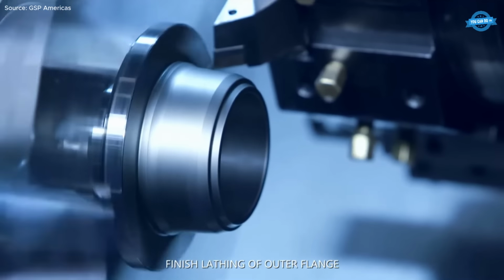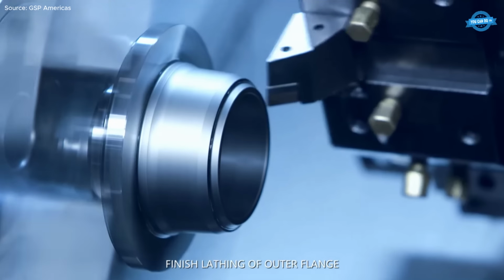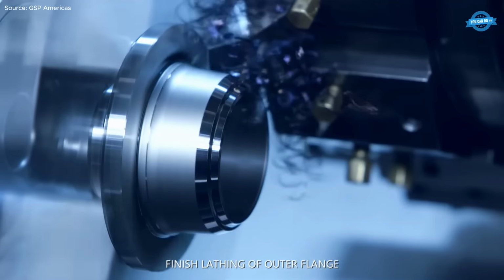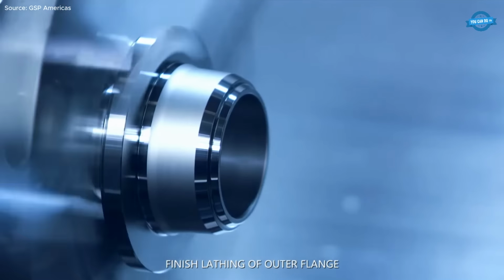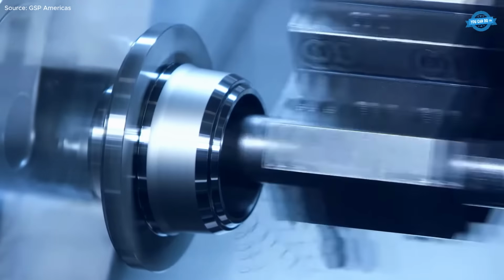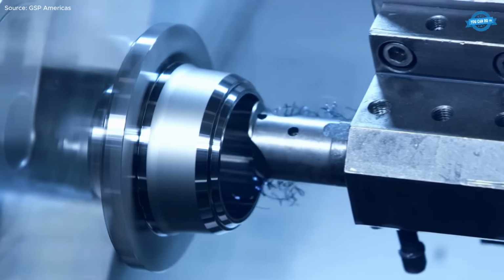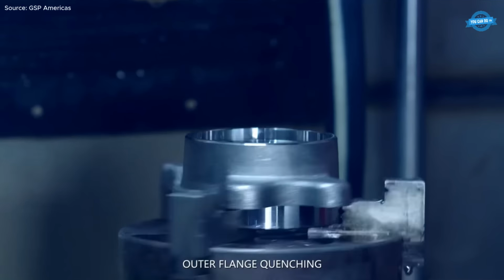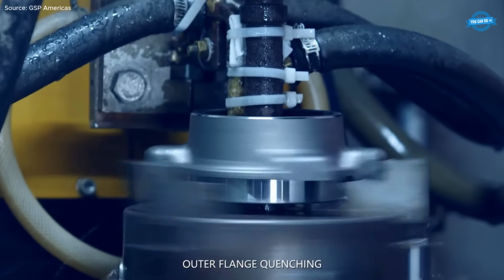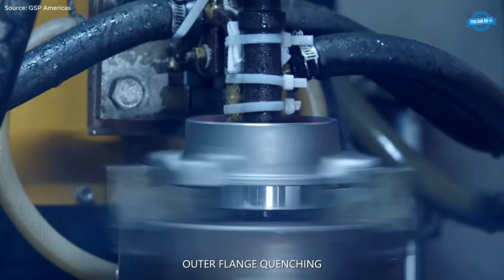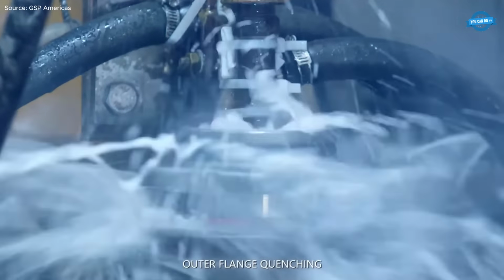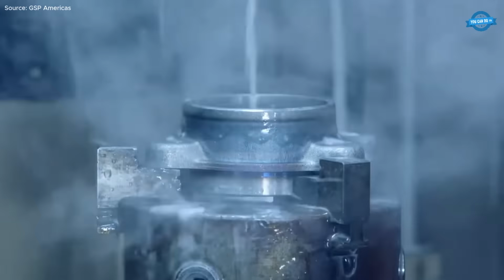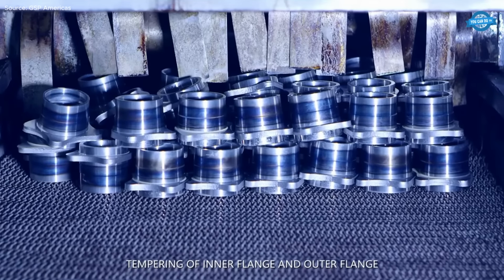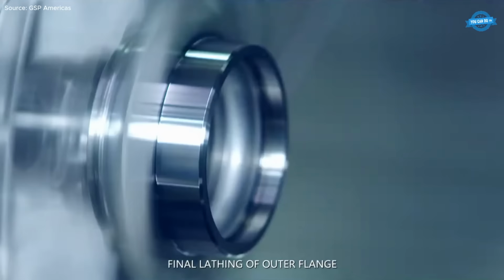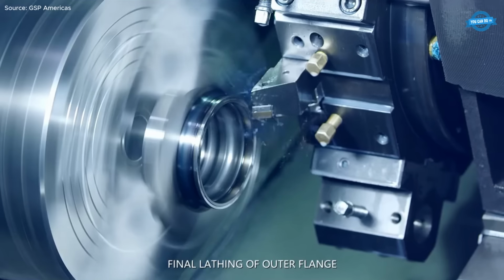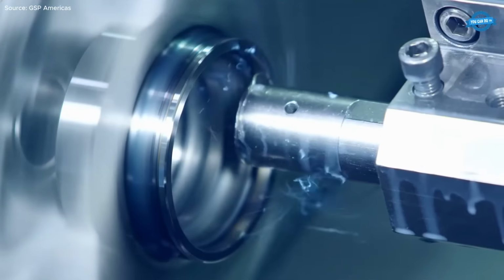GSP automotive wheel hub assemblies are produced through a tightly controlled multi-stage manufacturing process that integrates heat treatment, precision machining, surface finishing, automated assembly, and in-depth inspection. The process begins with finish lathing of the outer flange to establish base geometry, followed by quenching to achieve the required hardness and wear resistance. Both the outer and inner flanges then undergo tempering, relieving internal stresses and stabilizing mechanical properties before further machining.